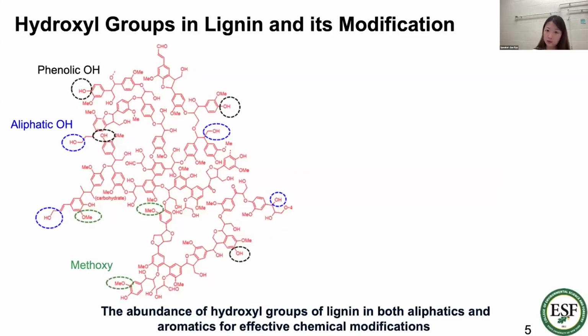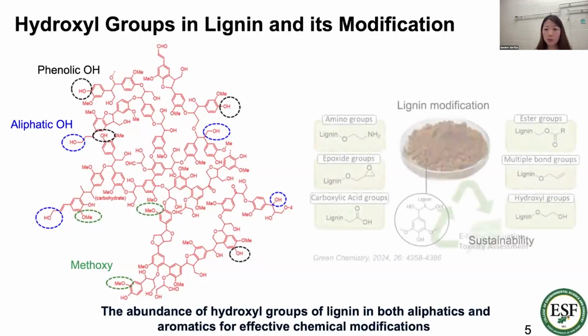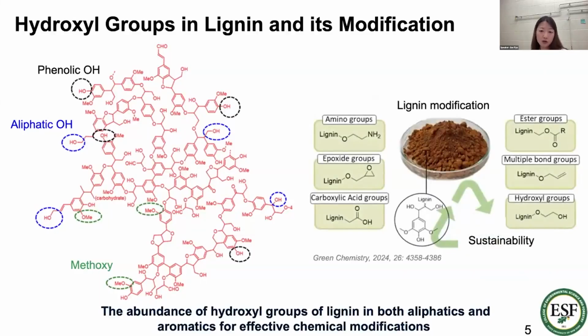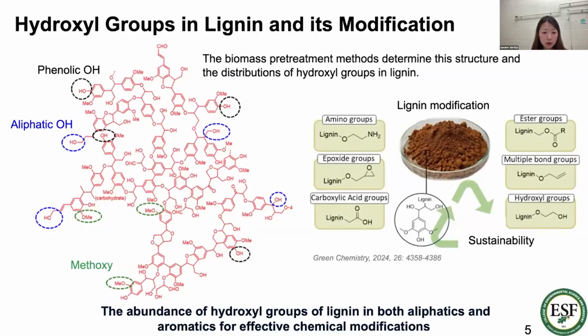We extracted lignin from the biomass resource, and how can we utilize it? We can modify the lignin, and many researchers try to introduce functional groups into the lignin structure to modify the lignin molecules. Lignin has two types of hydroxyl group: aliphatic hydroxyl group and phenolic hydroxyl group. People try to replace these hydroxyl groups with other functional groups. To exchange the hydroxyl group into another functional group, the composition of aliphatic and phenolic hydroxyl groups is important. The biomass pretreatment also determines these functional groups of the lignin structure.